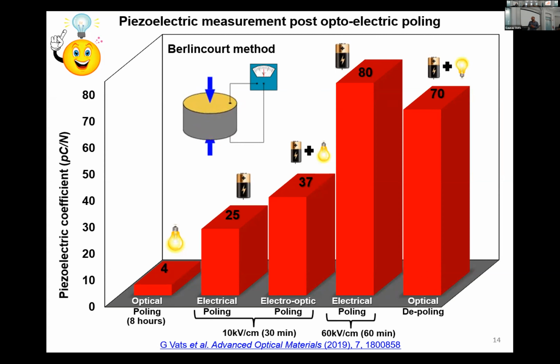How it happened? That's again the point that I explained in the mechanism. When you shine light, charges are generated, which are compensated by the movement of domains. And movement of domains means we are actually changing the state of polarization. So here what I did is I used this Berlincourt method to study the piezo response of the material. It's a macroscopic measurement. When the sample is not poled, we expect the piezo response to be roughly 0. And when I did this first measurement, it was just exposed to light, no electric field.